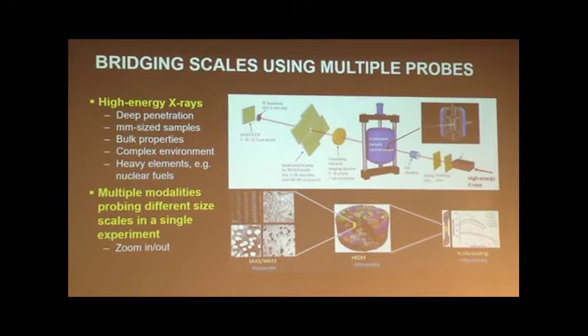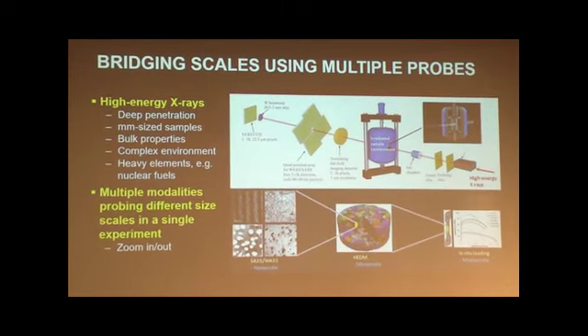With a high-energy X-ray, nowadays we can do the typical large-scale mechanical testing in the beamline. At the same time, we use X-ray to measure the microstructure. And using different detectors, we can not only measure one size of the scale, we can measure multi-scale. For example, in this case, we measure the lattice parameter, lattice strain, and also use small angle scattering technique to look at the nano-sized voids or multi-phases.